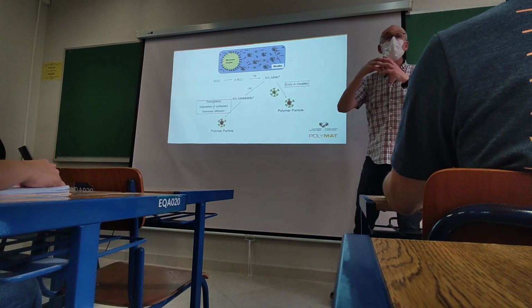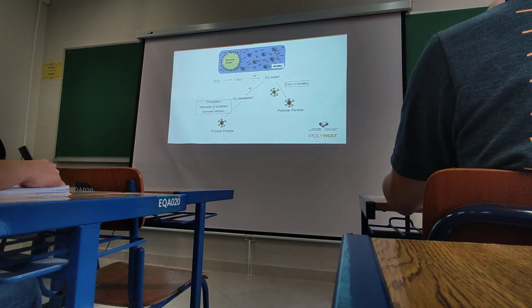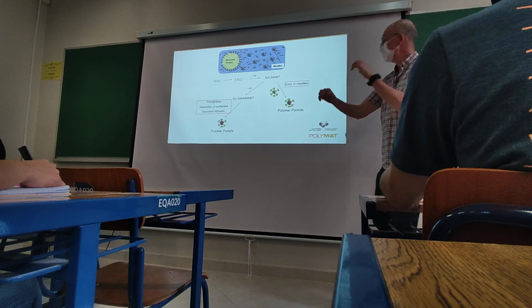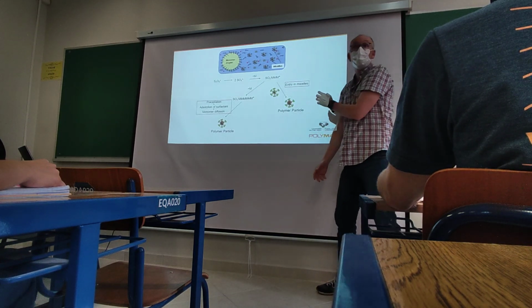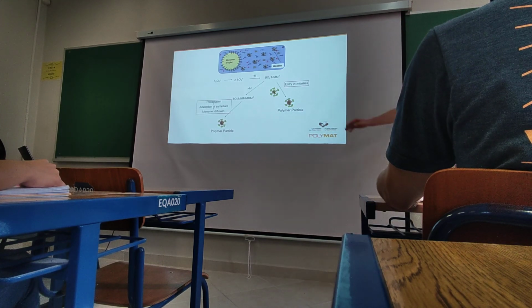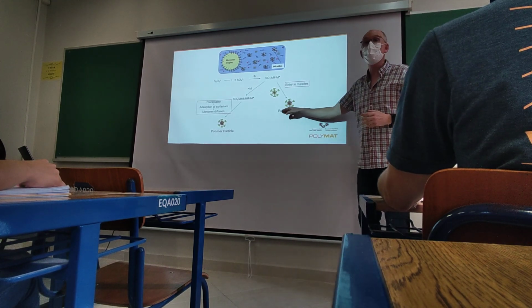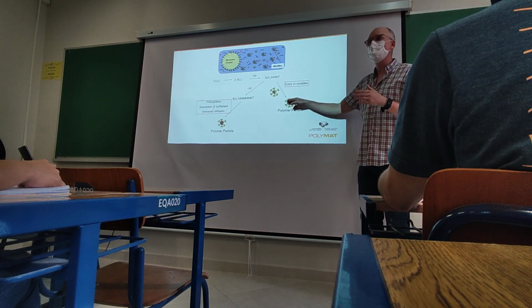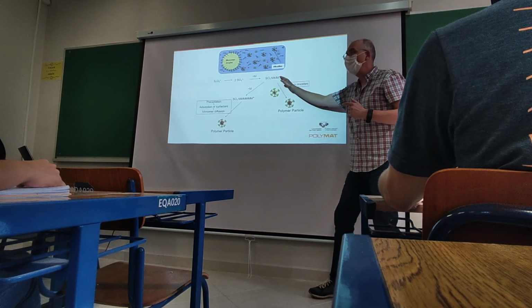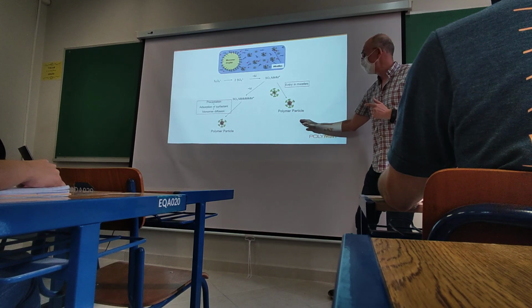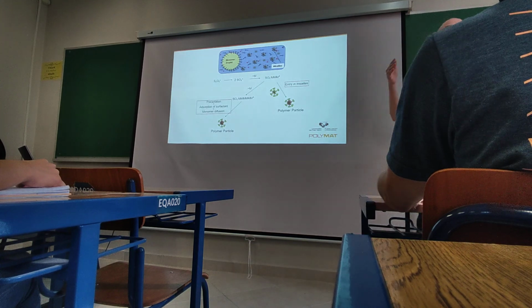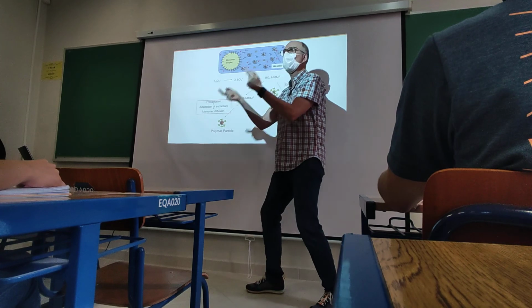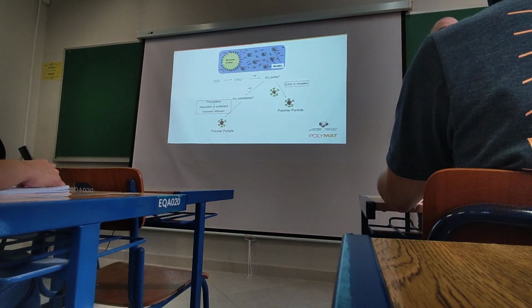When a radical enters to a micelle, it finds plenty of monomer, and polymerization starts in the micelle, and this micelle in which a radical has entered becomes what we will call a polymer particle. Okay? So this is a way in which polymer particles are formed in emulsion polymerization, by entry of oligoradicals into micelles. If there are no micelles, if you were working with surfactant below the critical micellar concentration, there is another way in which polymer particles can be formed.